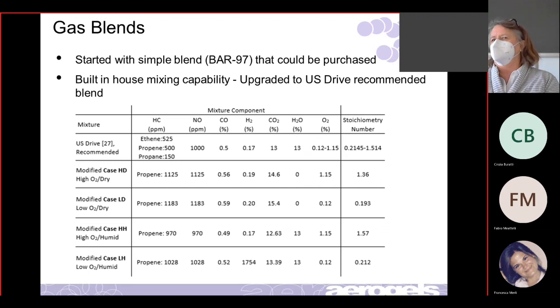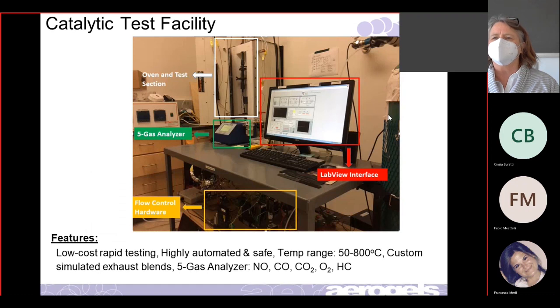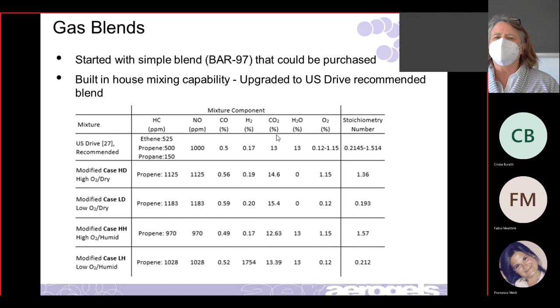But when we started doing a lot more testing, we decided to develop our own system and mix our own. We use what is recommended. There's an organization in the US that recommends anybody who does testing with catalytic converters use specific amounts of hydrocarbons, nitrogen oxide, carbon monoxide, H2, CO2, water, and oxygen. They specify that amount. Your HCs are in the ppms, and so are your NO, very small quantities. These are not good gases to work with, so we have to be very careful. All this is done in a hood. They recommend a mix of gases: ethene, propene, and propane.